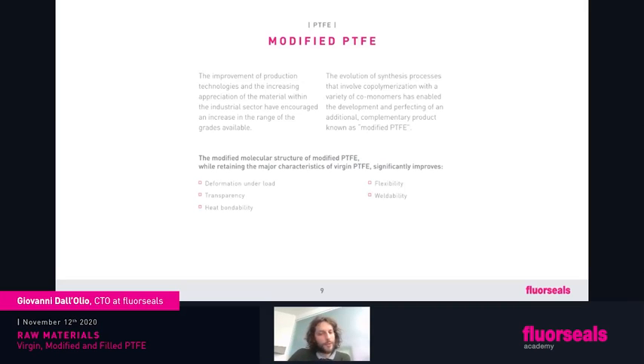Also, it's not mentioned here, but it's one of the key features of modified PTFE. I apologize if we didn't add it to the slide, but we will add it when we share the presentation with you. It's the better permeation resistance. So modified PTFE has better permeation resistance. This, for example, is really useful in seals because you don't want some of the stuff, be it a gas or liquid, going through the porosity of PTFE. Porosity is very low, so we are talking about the permeation of this gas through the bulk over years. Basically, modified PTFE has a better permeation resistance.